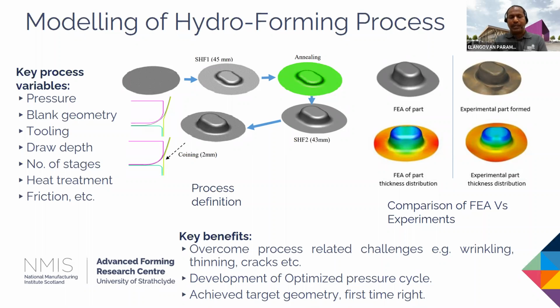And overall, the key benefit achieved for our customer from this modeling work is that we were able to overcome process related challenges, for example, wrinkling, thinning, and cracks. And then as explained by Diego, the definition of an optimized pressure cycle for the hydroforming is also an important one. Otherwise we have to do more trial and error approach. It would be quite an expensive and time consuming process. And finally, by doing this modeling development, we were able to achieve the target geometry first time. So with that I will move on to my colleague Hosam. He will talk about thermal analysis further.